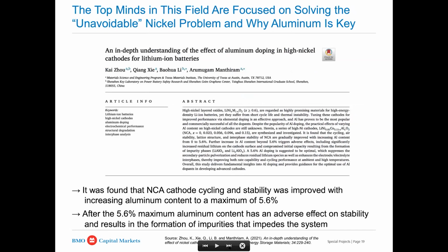Also, the top minds in the field have been solving what they call this unavoidable nickel problem, and why aluminum is key. This is a very interesting paper that came out, and this problem was talked about at great length by Jeff Dahn at the International Battery Seminar. It was found that NCA cathode cycling stability improved with increasing aluminum content, up to a maximum of 5.6%. Whether that is going to completely replace cobalt's ability to stabilize nickel, we don't know. But this is pretty interesting, and like I said, there are a lot of top minds trying to get cobalt out of the system. But the bottom line is that it's all about trying to tame nickel and trying to find the element that can tame nickel the same way cobalt has.